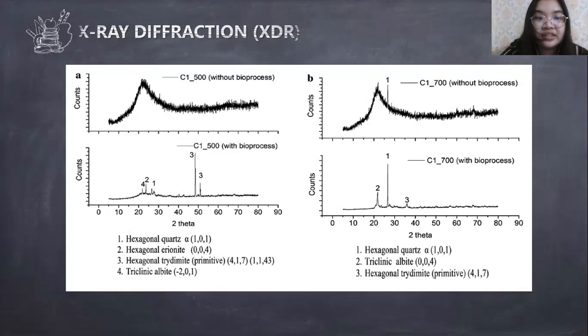Next, here it shows the diffractograms that came from particles of rice husk, sugarcane bagasse, and coffee husk. The crystalline nanoparticles were obtained by using two different temperatures, 500 degrees Celsius for A, C and E, while 700 degrees Celsius for B, D and F. Let's start with A. In this part, we put rice husk at 500 degrees Celsius. Here, we observe that while not using bioprocess, there is an amorphous structure, while crystalline phases can be found if we bioprocess it. Hence, it is possible to identify some diffraction planes from quartz and others such as tridymite.